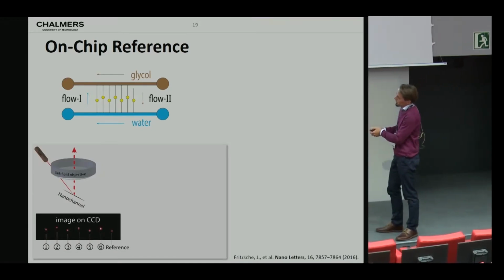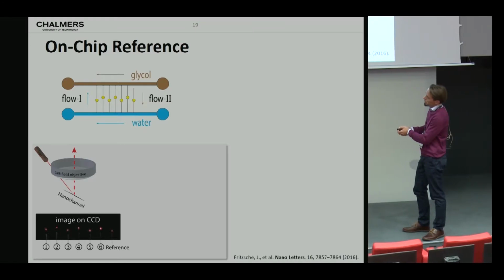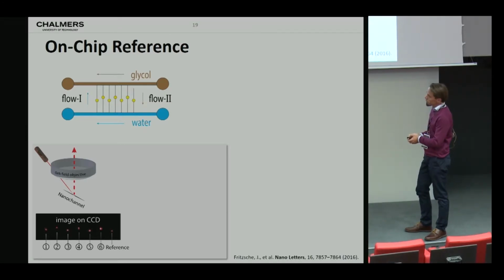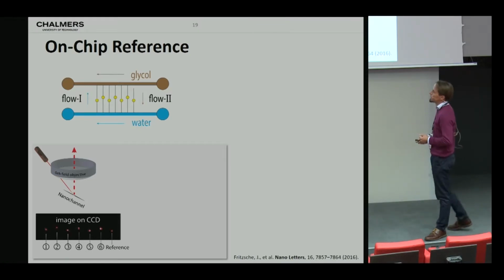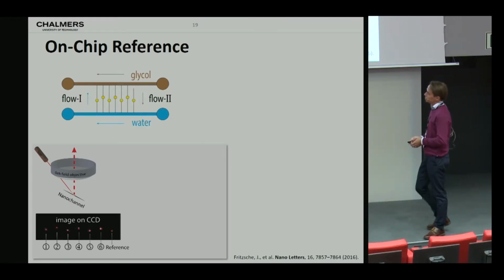First of all, we can now image these particles in the channel on our CCD chip. Note that we use monochromatic laser illumination, not through the objective, so we are here not going to measure peak shifts, but we're just looking at intensity changes in the scattering at the specific wavelength. And we have our 6 sensor particles and the reference particle in this channel.